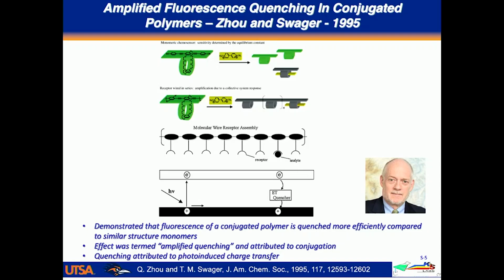they showed that the interaction between the polymer and that quencher, a quencher for fluorescence, gave rise to what they called amplified quenching. Basically, the idea is that if they compared the efficiency by which the viologen quenched a monomer compared to a polymer, the polymer was quenched in the range of 100 times more sensitively for the same amount of viologen added. And they coined this amplified quenching, and this paper that came out in 95 had no application. It was just a fundamental study, but it gave rise to the concept of getting enhanced sensitivity in quenching if you used a polymer combined with a fluorescence quencher.